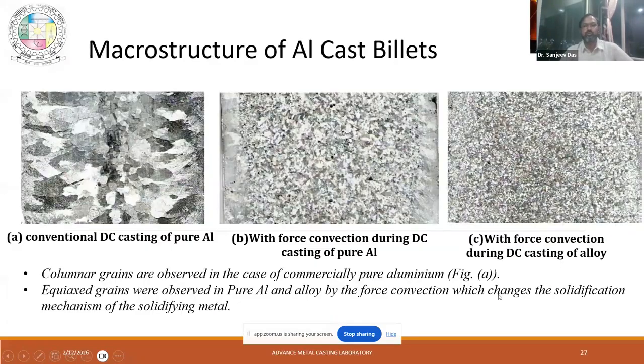Now let us show you the macrostructure. If there is no rotor-stator device, you get big columnar grains, random grains. In the center there are fine grains, at the side there are fine grains, then in the middle you have the columnar grains. When you start forced convection, all the structure changes into a fine grain structure, and for alloys it is even finer. So this is the beauty: without using any grain refiner, by just introducing forced convection, you can change the structure. You are decreasing the grain size, and by decreasing the grain size you are increasing the strength of the material without changing the chemical composition.